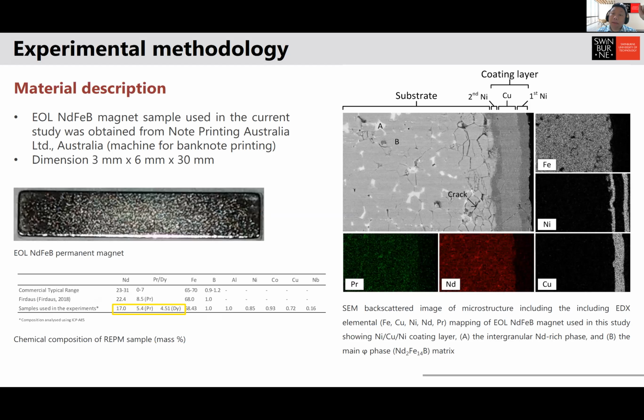So in here we have the magnet. The one on the right is the magnet I mentioned. In practice, the actual magnet has a thin layer of coating on the surface, right? So it can be nickel, copper, nickel, such as shown in here, and it can be other metal coating. The purpose of the coating is to improve the corrosion resistance of the magnets, especially high temperature corrosion. Yeah, when it gets hot, so that it's not oxidized and not breaking down. So that's the purpose of the coating. Now, as you can see, the coating is pretty thick. It's about 10 micron, I believe.